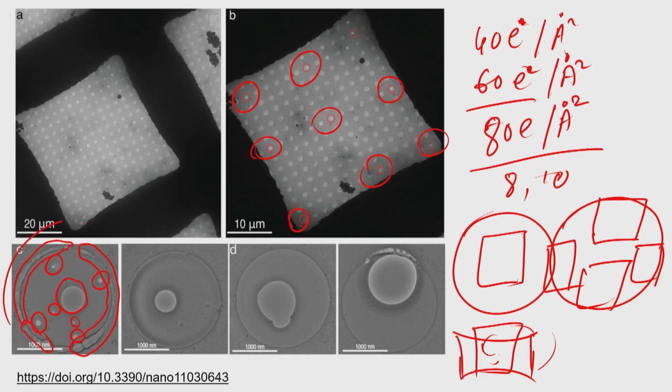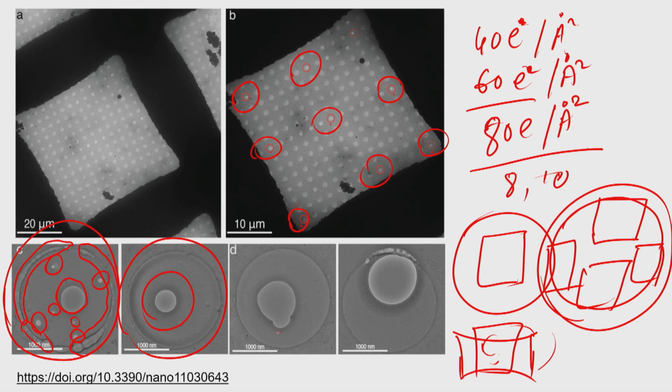But if the stability increases like that, then definitely per hole we can image 4, 5, 6, whatever it is possible, and we can cross-check whether it is damaging our sample or not. Here also you can see this is a hole where we just gave one very long exposure. You can see bubbling effect, that the water started boiling there basically.